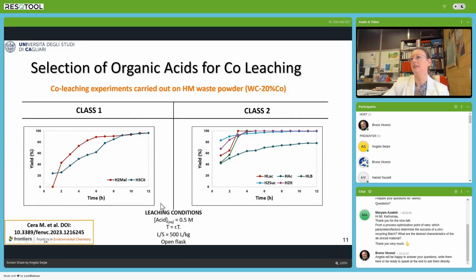So here you can see the behavior of the two classes of agents. In particular, class 1 is able to dissolve the metal in water, but also class 2, because in water a certain amount of oxygen is dissolved. Of course, we also observe that forced aerating conditions may help the efficiency of the reaction. This classification is important because it means that when we have oxidizing acids, we can work also in solvents different from water.